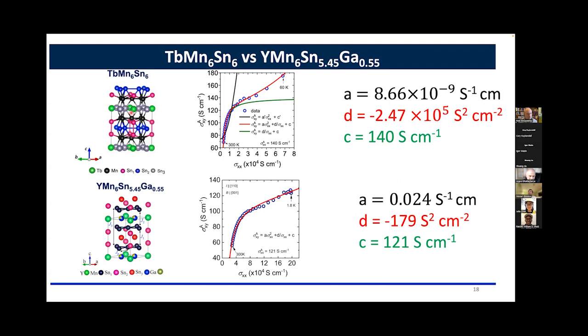This is the line compound. This is a disordered system. This is what you would expect when you introduce disorder, to have these impurity-carrying terms much larger in a system. Look into the C term, which is coming from the band structure. It's 140 Siemens per centimeter in terbium manganese 166. In this compound, it's 121 Siemens per centimeter. And it's also understandable because the disorder might have messed up the bands a little bit. But in the ballpark, it remains the same. And then look into this D term, which we thought was coming from the fluctuation, right?